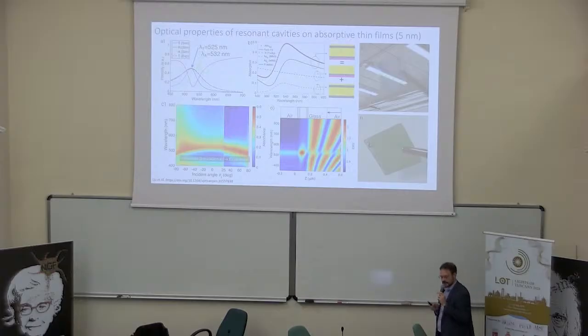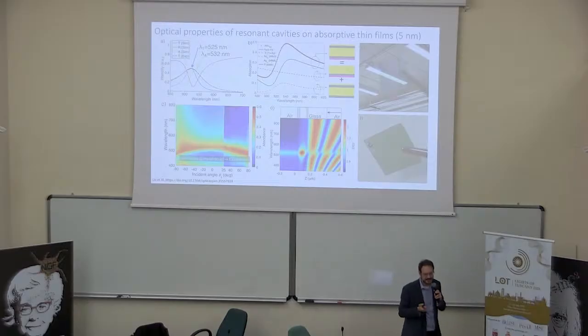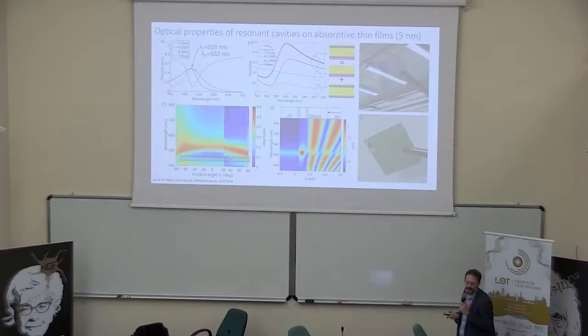Because if you consider that this system is mainly made by a metallic layer that is repeated 2 times, what you expect is a mirror. But you start to open a window where these materials transmit more or less than 50%. And thanks to the titanium layer, if you take just the titanium plus silver alone, you get an absorbance that is flat.